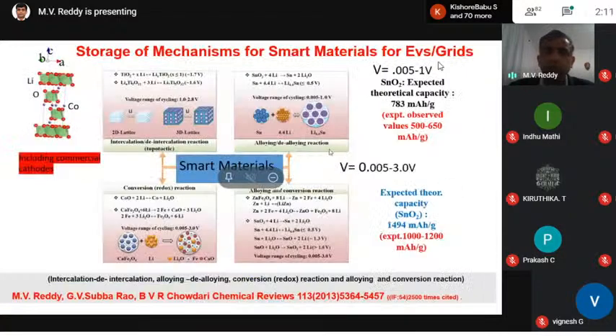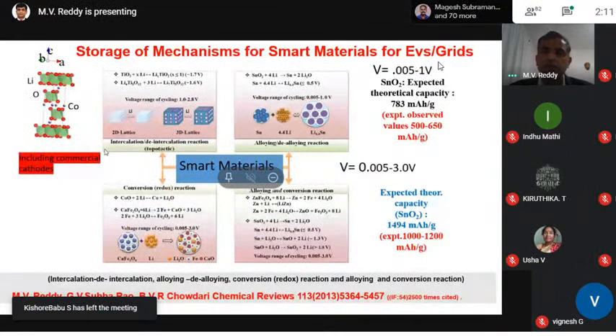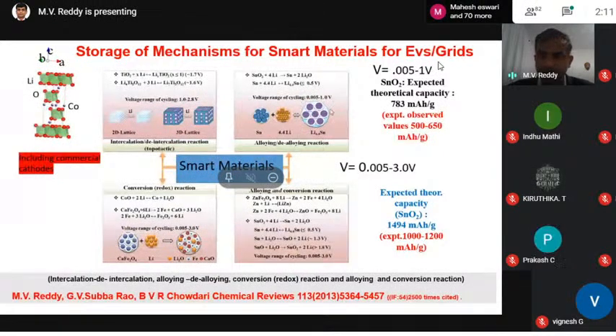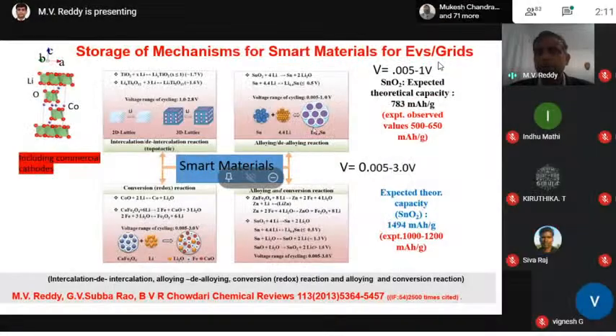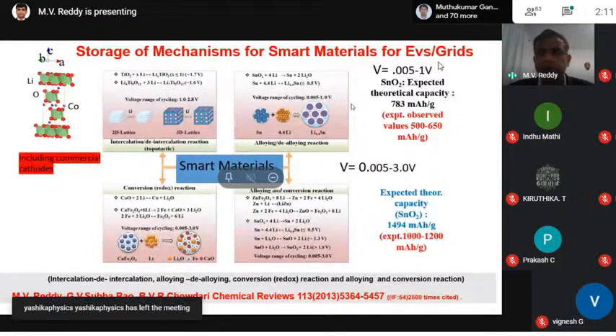Again, the storage mechanisms are broadly classified, and in fact there are four types of mechanisms. Among them, commercial energy storage mainly works on intercalation and deintercalation reactions, in the sense that we get less volume variation. If you talk about silicon, we see expansion. Silicon and tin are alloy-forming elements. Then there are conversion-type oxides, and I'm going to discuss a few examples at a later stage. For alloy tin-based oxide, if you cycle between 1 volt and 3 volts, the theoretical capacity varies depending on the voltage window used for cycling.